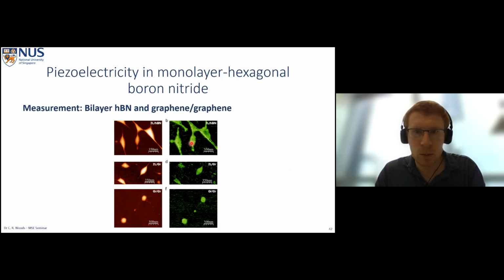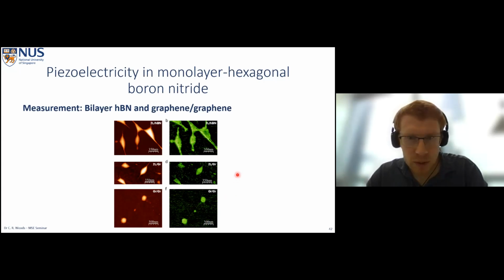when we return to the bilayer boron nitride system, we get back to a centrosymmetric unit cell again, so we don't have any piezoelectricity. And of course, for graphene, we don't have any polar bonds at all, and electrons are allowed to move, so we shouldn't see any effect of piezoelectricity for graphene either. So this is just to confirm that our measurement is really working only for monolayer boron nitride. We don't see any signal here for these 2 other systems as expected.